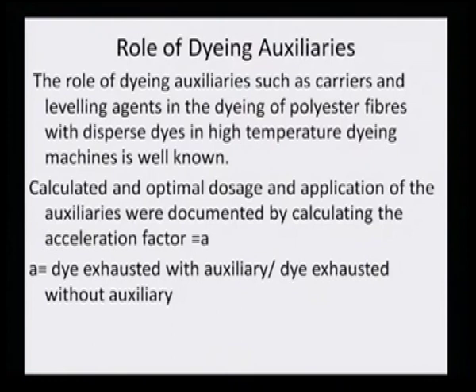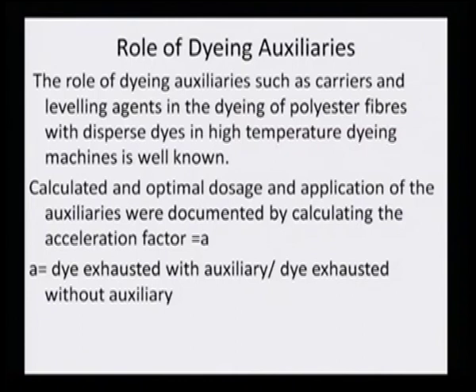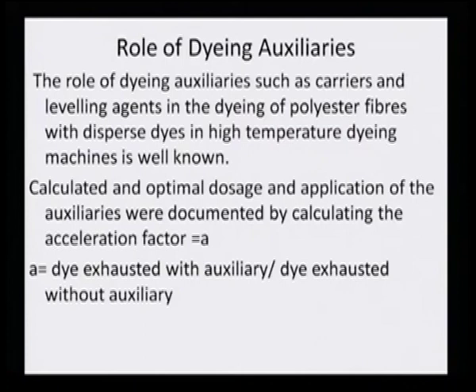Dye auxiliaries play a very vital role. The role of auxiliaries such as carriers and leveling agents in the dyeing of polyester fibers with dispersed dye in high temperature dyeing machines is well known, because facilitating chemicals must be added for swelling of the fiber and dispersion of the dye molecule. The optimal dose is documented by calculating the acceleration factor A, where A equals dye exhausted with the auxiliary divided by dye exhausted without the auxiliary.